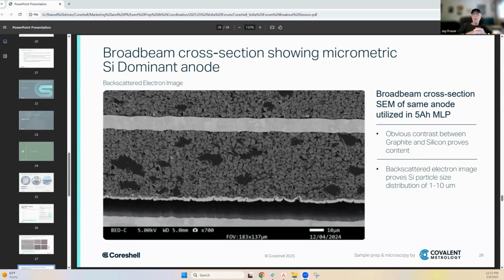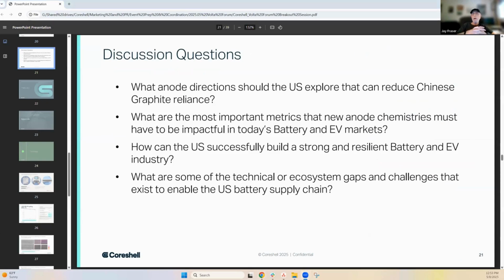Yeah, well, it's more of a comment and in addition to what you've been talking about. We are not a battery company. We're an electrolyte solvent company. We're doing inorganic liquids that are not ionic. It's a pure liquid. And David, Jonathan, we've actually had some really good experience with silicon anode materials, starting with a 30% silicon graphite with a nickel-rich, more than 811 cathode. We demonstrated out to 620 cycles at slightly better than 85% capacity with our additive, well, it's not an additive,